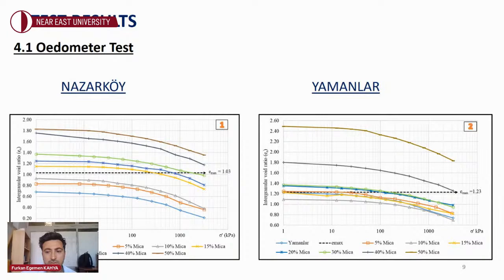Threshold fine content can be found on the intergranular void ratio to effective stress plane as the fine content where the compression curve converges to the maximum void ratio line. Threshold fines content of Nazarköy and Yamanlar correspond to 12.5% and 17.5% mica percentages.